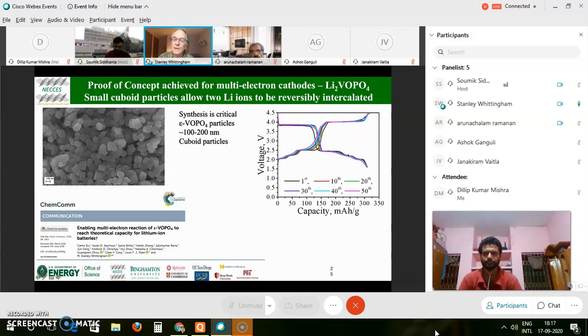And this has no effect on electrochemical behavior, except that when you're actually moving lithium ions, this becomes single phase, so it's very high rate. And the key point to note here is the black curve is the first cycle. The purple curve is the 50th cycle. There's no difference. So we have now proof of concept. We can stuff or intercalate 2 lithium ions into a crystalline lattice without hurting that lattice in any manner. So we've got proof of principle here. We've now got a few other challenges to make this material work.